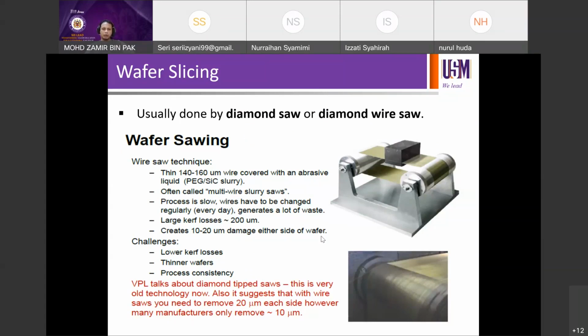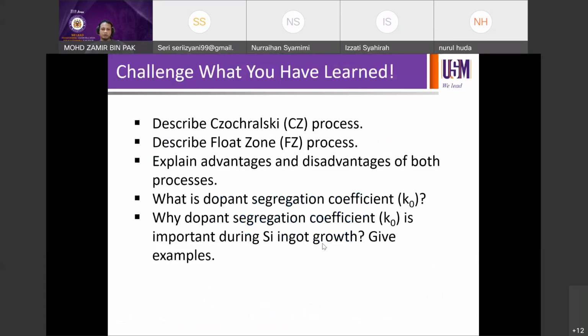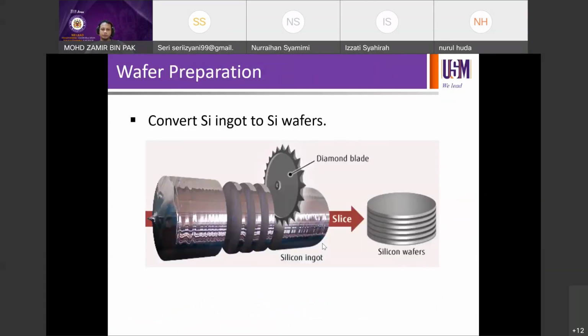We can use multiple techniques for the slicing process. If you can see from this first slide for this topic, we can use a diamond blade, for example, in order to cut the wafers into a specific thickness. The thickness is determined by the foundry, if you like, and the wafer fab. Typically for wafer fab operation, we use a thickness of around 500 micron in order to do the fabrication process.